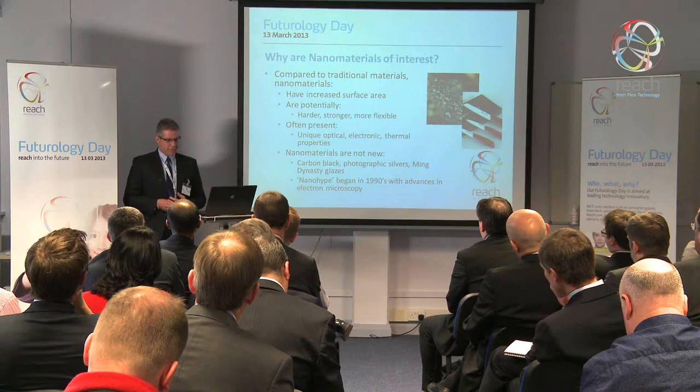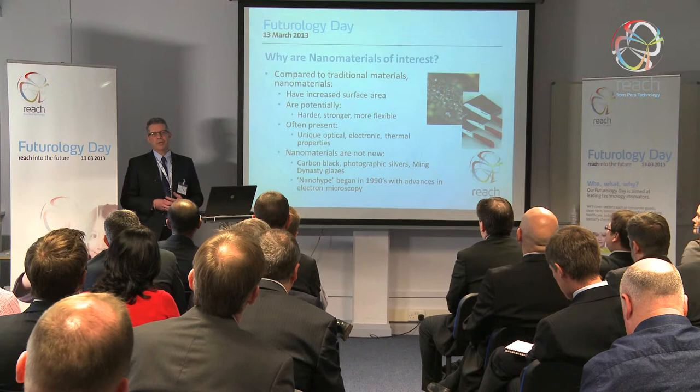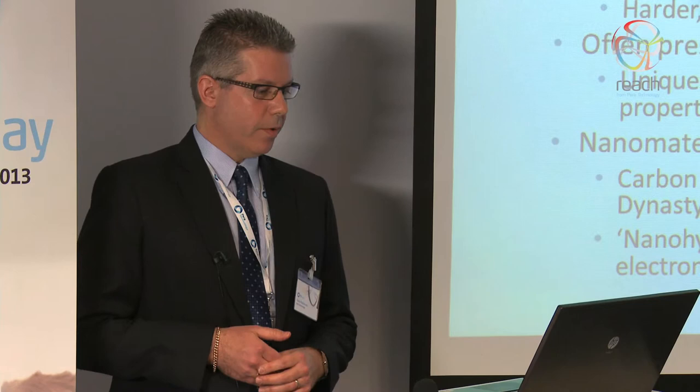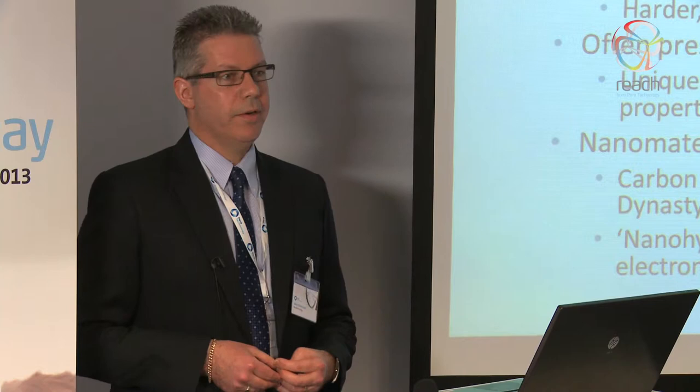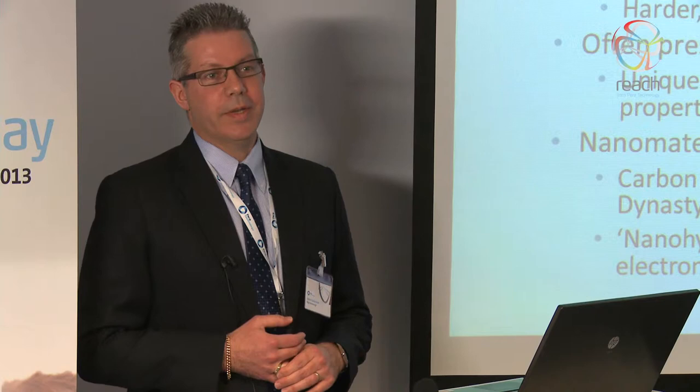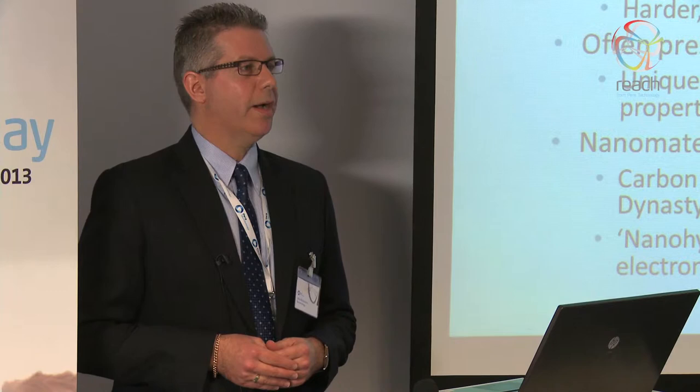I would like to say that these materials are not new — nanomaterials have actually been around for years. The carbon black material that's been used for many years to reinforce car tyres is actually a nanomaterial, though this probably just wasn't very well understood 50 or so years ago. Photographic silvers in traditional photography were actually colloidal dispersions of nano silver. And there have even been examples found of glazes used in pottery on ceramics from way back in the Ming dynasty in China which actually contained nano-scale pigment. So these things have actually been around for centuries.